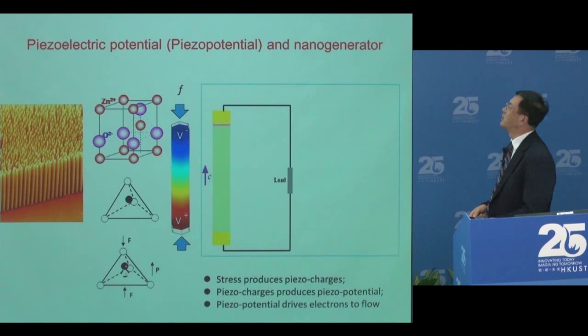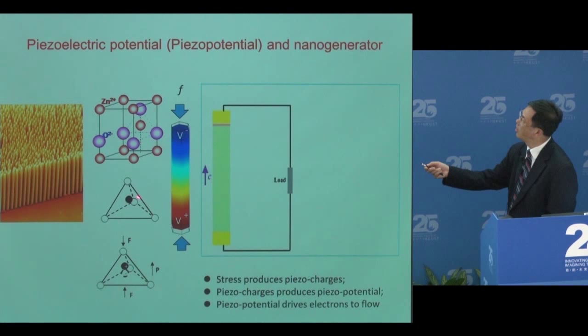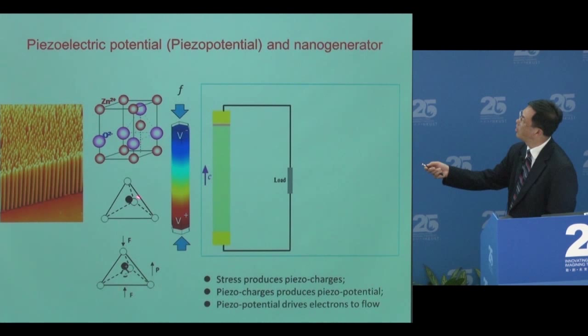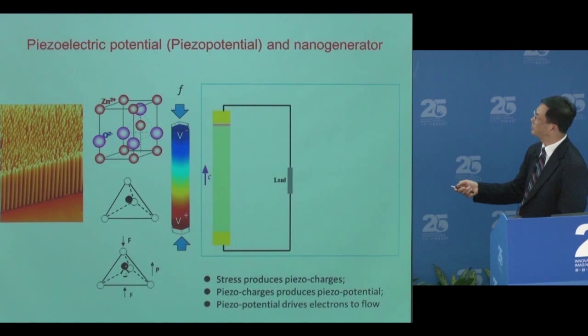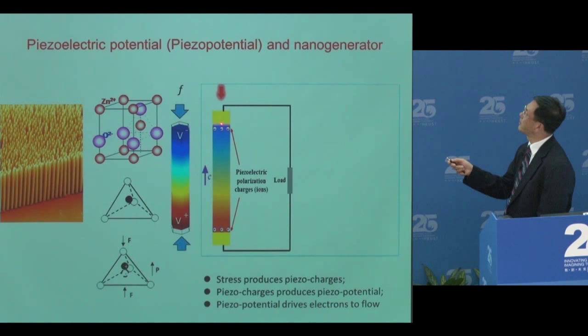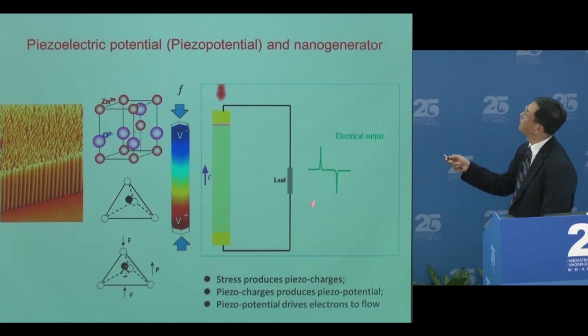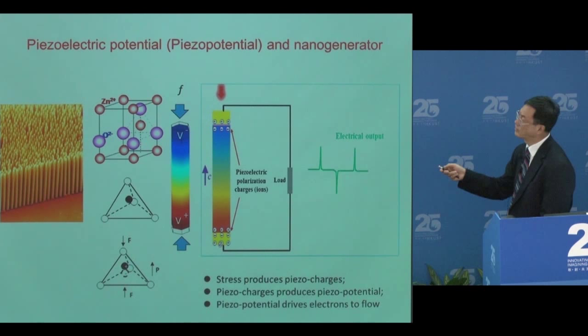We grow zinc oxide materials — many faculty in this university grow this material as well. This is a material lacking central symmetry: cations and anion centers usually overlap, but under mechanical force it polarizes, giving a dipole moment and a piezoelectric potential along the body. When mechanical strain is applied, polar charge creates an interface, driving electrons to flow through an external load to screen the polar charge. On release, electrons flow back — this cycled motion is the fundamental mechanism of the piezoelectric nanogenerator.